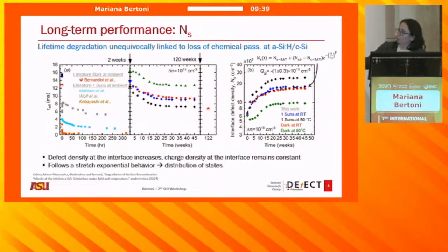And so a little bit of what you see in here is basically a year and 2 years of tracking this surface recombination velocity as a function of time under different conditions. So let's just pay attention to the blue and the black, which are basically 1 sun at room temperature and 1 sun at 80 degrees Celsius.